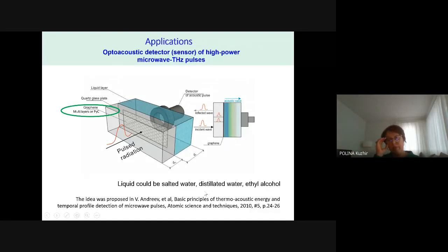Another interesting application for the same material, graphene placed on top of a dielectric of proper thickness, which provides almost perfect absorption, is an optoacoustic detector for high power microwave and terahertz pulses.